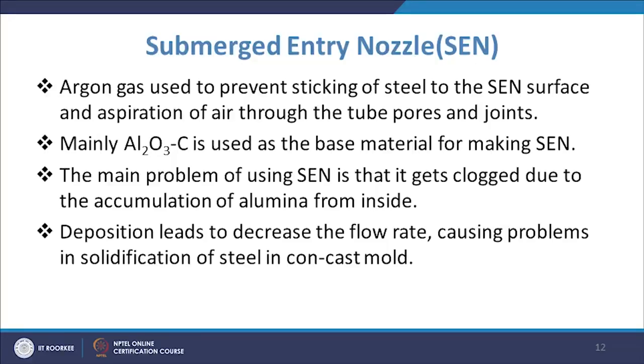The main problem of using the SEN is that it gets clogged due to the accumulation of alumina from inside. Many a times the alumina coming through causes clogging in the SEN, and that leads to a decrease in the flow rate, causing problems in solidification of steel in the concast mold. That is really a challenge, because if there is clogging, then there will be a decrease in the flow rate of the steel coming through the SEN ports. That is because of the inclusions or the alumina which is accumulated.